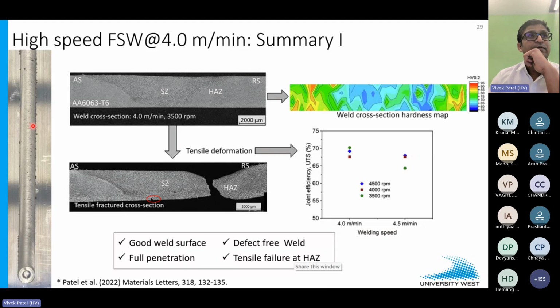You can see the weld surface, and we almost managed this butt joint without any flashes. And when we check the cross section of the 3 millimeter thick plate, you can see there is no lack of penetration, there is no defect. So the weld cross section provides promising data as a result of the tool and the right parameters.